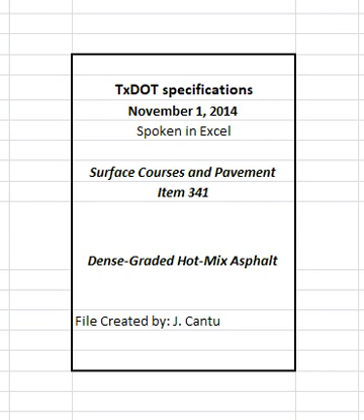4.9.3.3.4 Recovered Asphalt Dynamic Shear Rheometer, DSR. The engineer may take production samples or cores from suspect areas of the project to determine recovered asphalt properties. Asphalt binders with an aging ratio greater than 3.5 do not meet the requirements for recovered asphalt properties and may be deemed defective when tested and evaluated by the construction division.